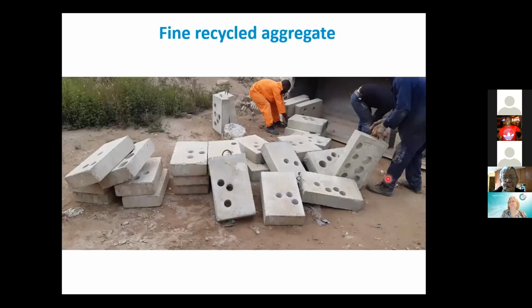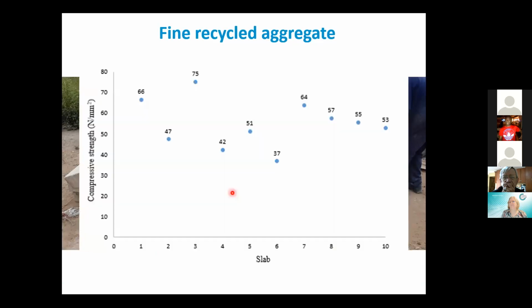So these are my recycled aggregate materials. This is the parent concrete that was obviously crushed for this work. The parent concrete comes from culvert slabs that were used as wing walls and culverts for a road project on the N2. These concrete slabs were first cored to obtain compressive strength. You can see the coring there. Some of them were tested, and these are just a representation of the average strengths. So we can see that the strengths typically vary between 37 megapascals and 75 megapascals.